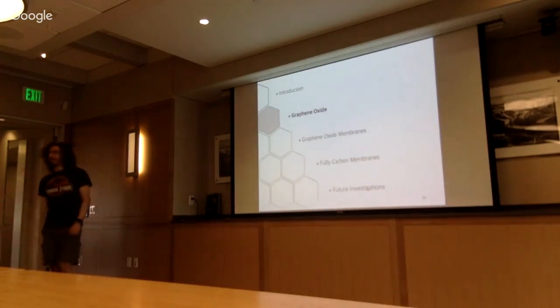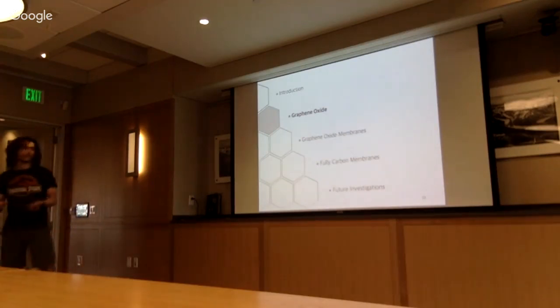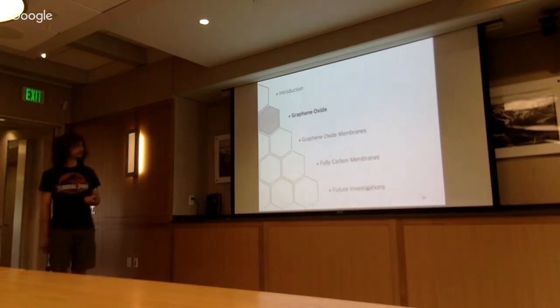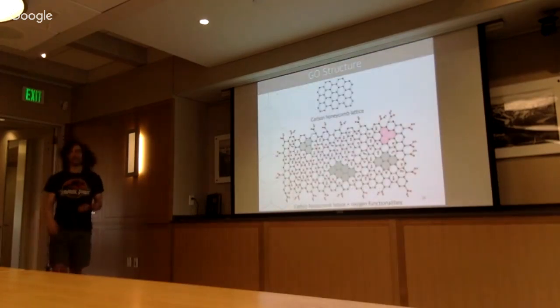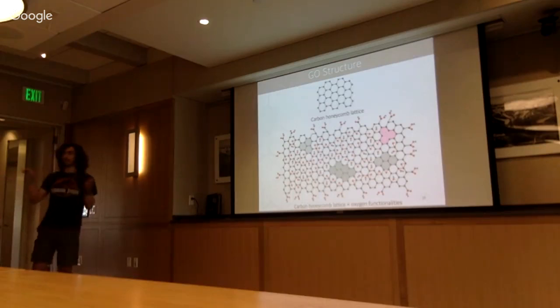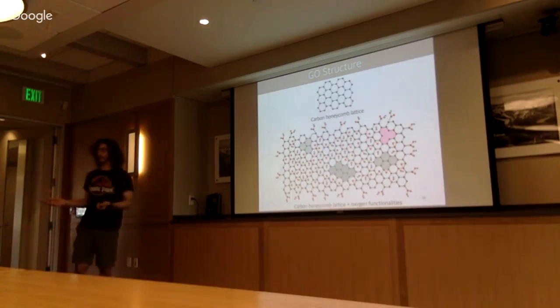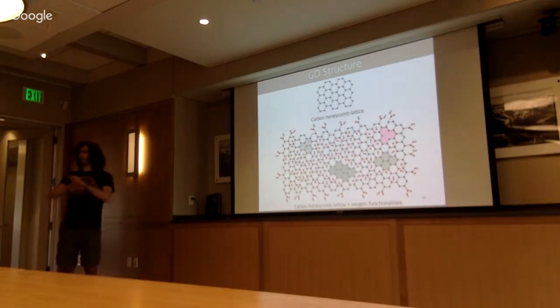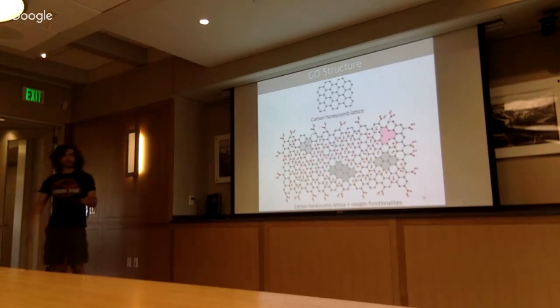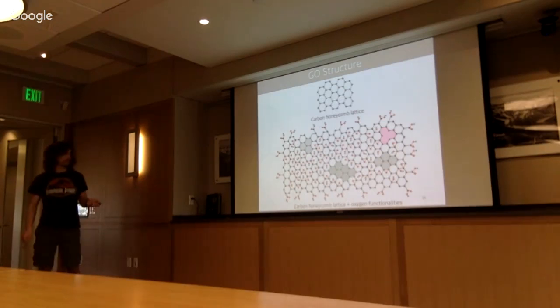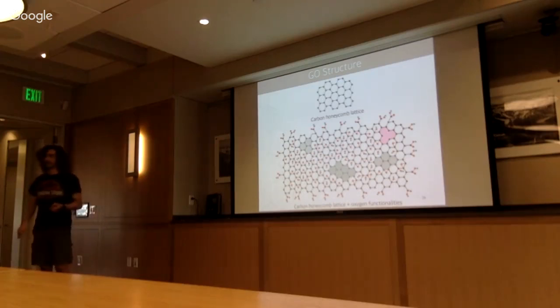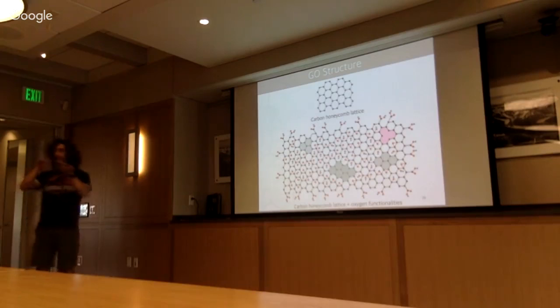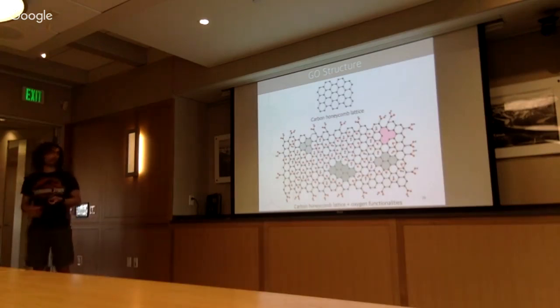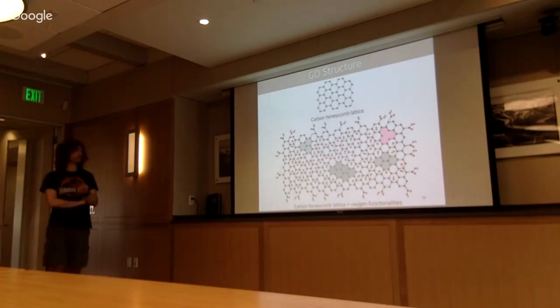So now that this was the end of the introduction, let's dive in and understand more what graphene oxide is. So graphene oxide is a monatomic material, so one atom thick, and all the carbon atoms are arranged in a honeycomb lattice, or sp2. However, this is graphene oxide, so that means you have oxygen functionalities, especially on the edges some carboxylate groups, and on the basal plane you have epoxide and hydroxide. So just think of it as a graphene sheet, but with some oxygen functionalities that decorate this graphene sheet.